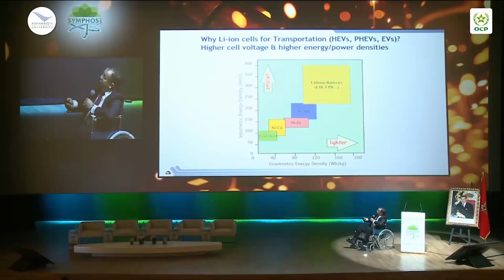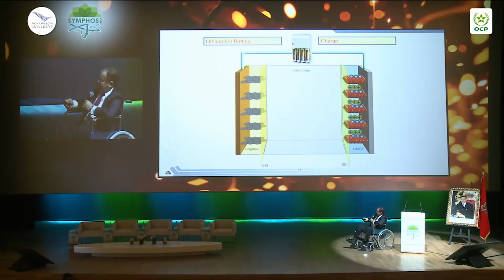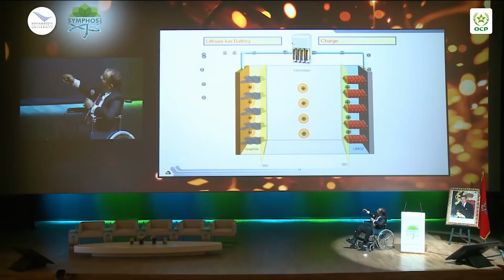And for people who don't know the concept of lithium-ion, I have a small schematic representation. The lithium-ion cell has a cathode with a layered structure, where lithium is sandwiched between metal oxide slabs, and carbon as the anode. Carbon also has a lamellar structure. So during the charge, lithium will move and be conducted through an electrolyte, which is a non-conducting media, and intercalate into carbon. And the electron will move this way.